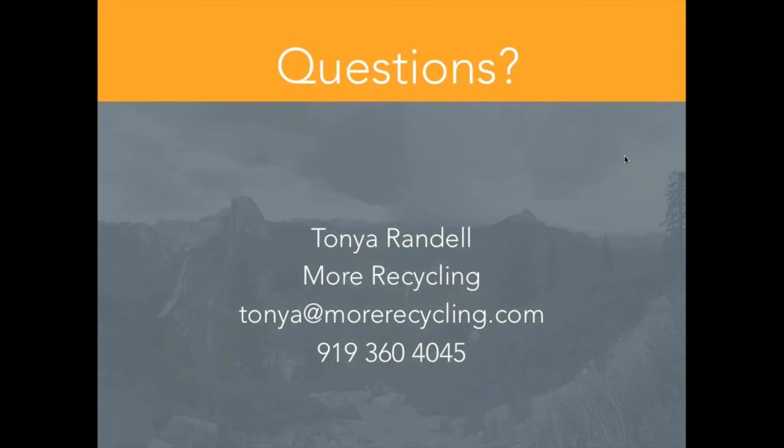Yeah, sticking to the foam theme, how do you densify polystyrene? What's the equipment used? So there are a couple. There are different levels. One of them is a cold press, and then one of them is a heat press. But the idea is basically that you take a bunch of polystyrene, typically not packing peanuts, but it's going to be block or the takeout containers, and they go in. They can either be shredded or ground, or they go in solid, and basically it just uses a big press, either with heat or just pressure, and it presses out all the air, and then it comes out in a block, or as that kind of toothpaste tube squeezed sort of thing, it kind of gets extruded that way.